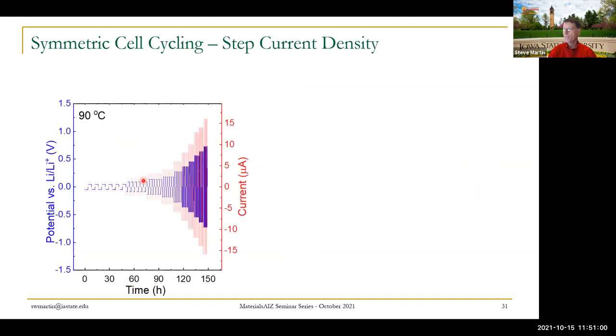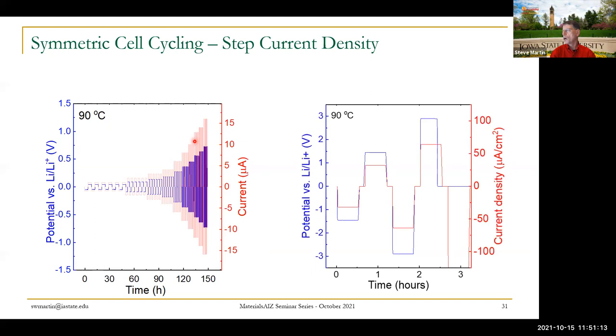We can push them. I think that's what's coming up here. We can keep pushing these things to see where they fail. We go up to 90 degrees and that's what we're doing here. We got up to about 15 microamps in this case, and it didn't fail. So we pushed it even harder and we got up to about 100 microamps per square centimeter. And finally, you can see right here, at about 100 microamps at 90 degrees, this glass failed.